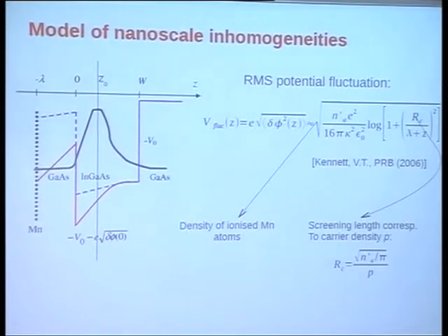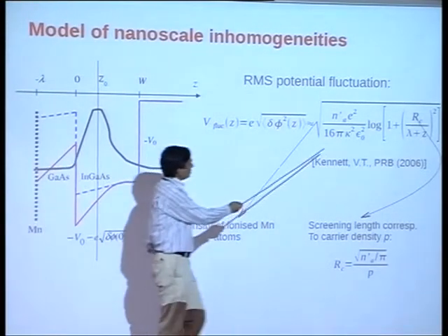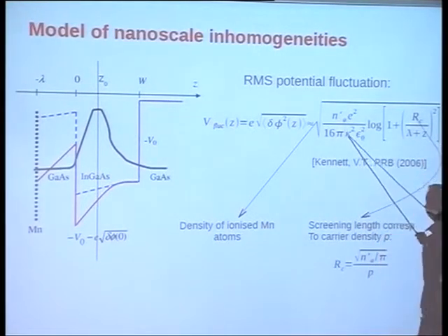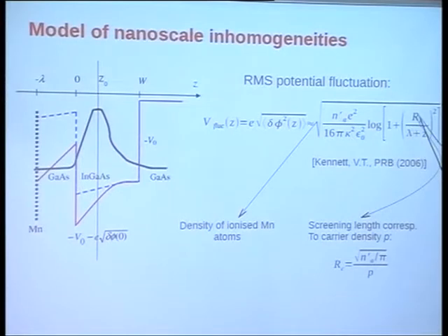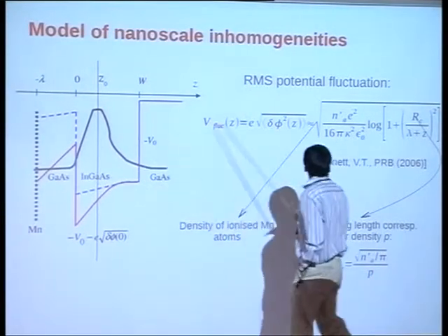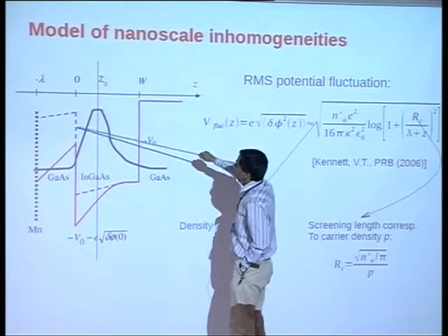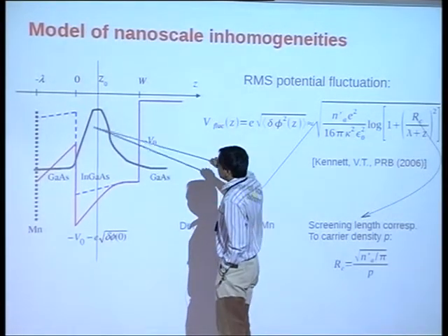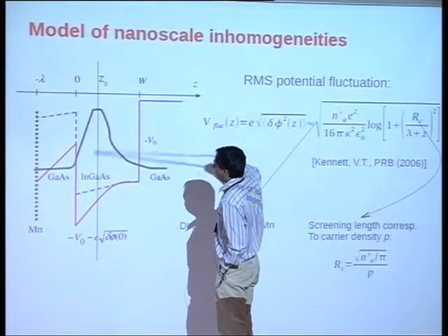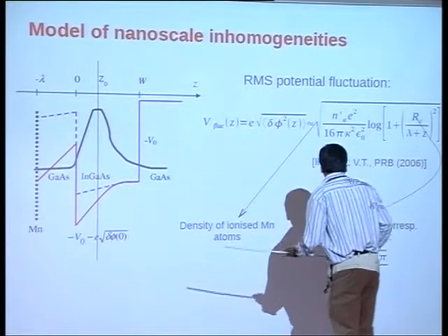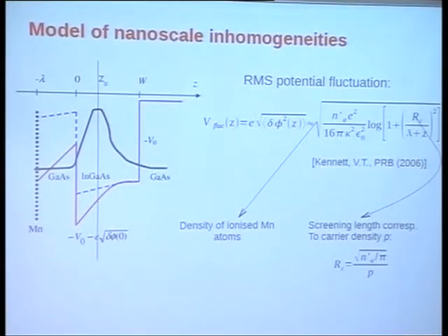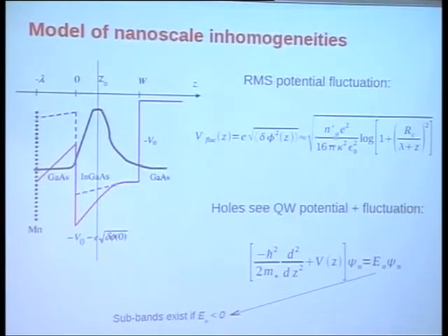One can easily work out the fluctuation potential. This is the RMS value, and it depends on the device parameters and doping density, dielectric constant, etc. And this is the characteristic screening length we have corresponding to a hole density P. Notice that if my density becomes larger, the screening length becomes smaller. And this lambda is the distance from the quantum well. And this Z actually is this distance, because the wave function doesn't exactly sit here. It's largely centered around some Z naught inside the quantum well. So we are looking at potential fluctuations at that scale.